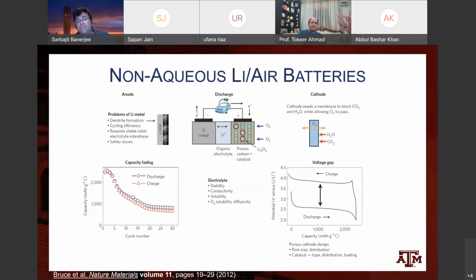Once again, since you're going to use lithium metal, dendrite formation is an issue, safety is an issue, you need to control the SEI phase, cycling efficiency is an issue. But then on the side of the cathode, you also need to have a catalyst, so the kinetics is a major challenge. You need a catalyst that is able to effectively reduce the oxygen. So what catalyst will you use, the distribution, the loading, how do you have a pore size that allows for this oxygen reduction, and of course needing a membrane to separate water and carbon dioxide and oxygen.